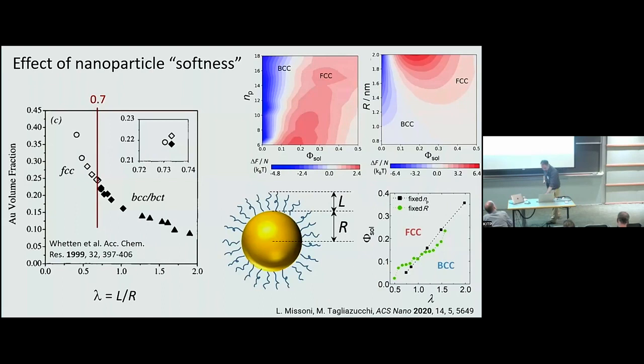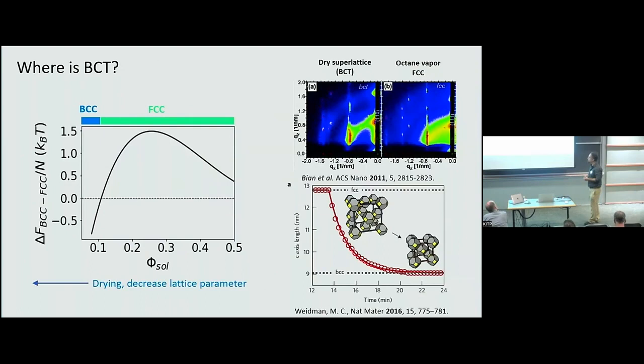All right, so I would like now to go back to this problem of BCT. As I mentioned before, BCT and BCC are not exactly the same. And in most experiments, the BCT phase shows up between BCC and FCC. So, for example, take this particular example. You have FCC when the superlattice is swollen, and then it goes to BCC. But everything in between is BCT.